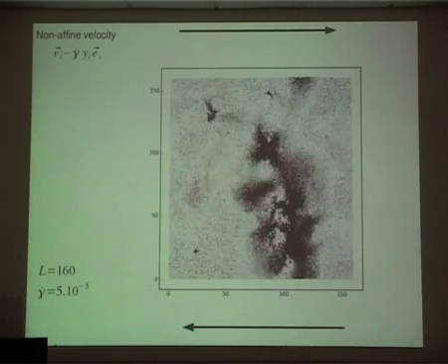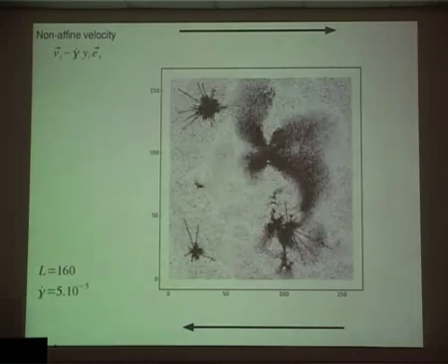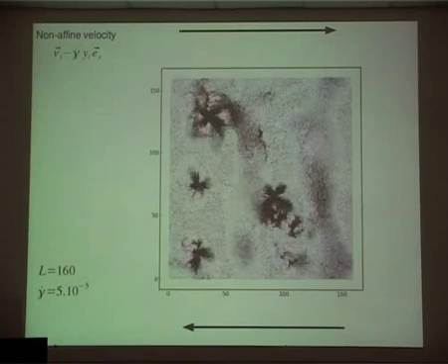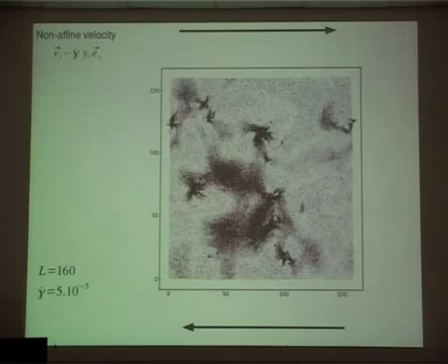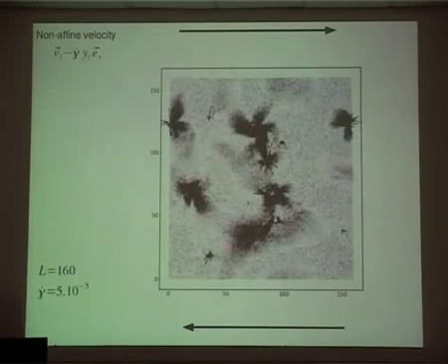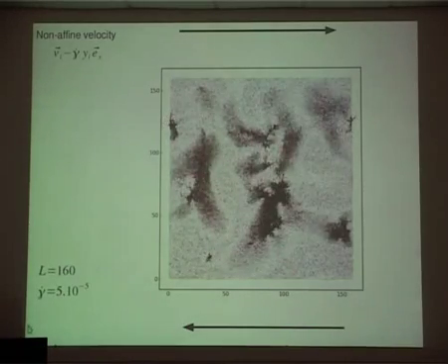And we know the shear modulus in the system, so we know the sound speed. We know all the moduli. And these waves actually are propagating at the shear wave speed. So they are really shear waves. So what you see is sound.